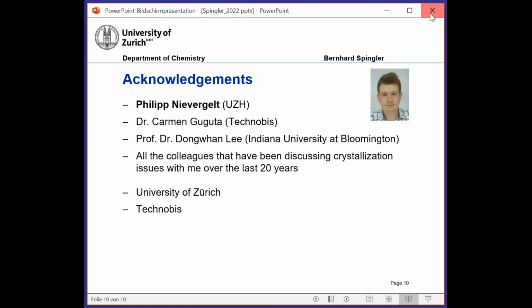Anthony is writing. In case of the sublimation, what is the realistically least amount possible from powder to obtain crystals? And would this amount be different for difficult to crystallize compounds? If so, which is the microgram amount that was successful? The only thing you have to make sure when you're using smallest amounts is, for example, to put in seed crystals, or to make sure that this small amount vapor deposits onto these crystals or a special area in your experiment. But you can try starting with one crystal if you don't have more material. Okay, I think that makes sense.